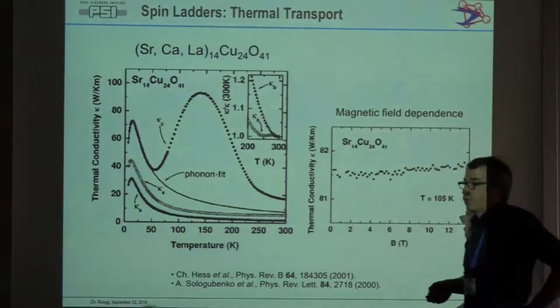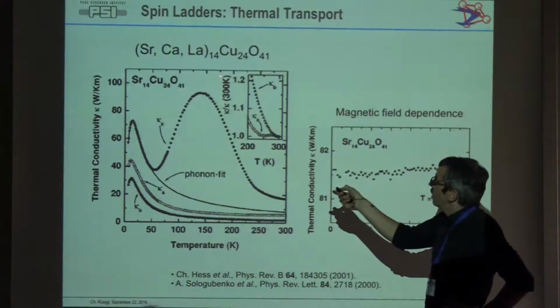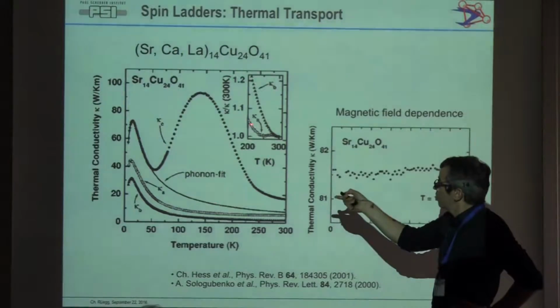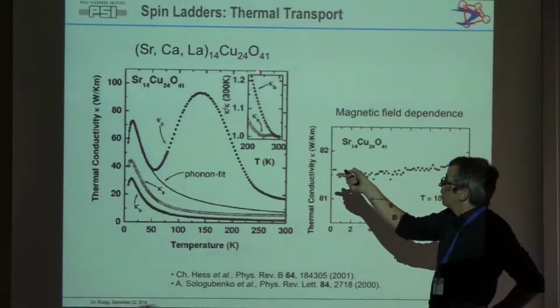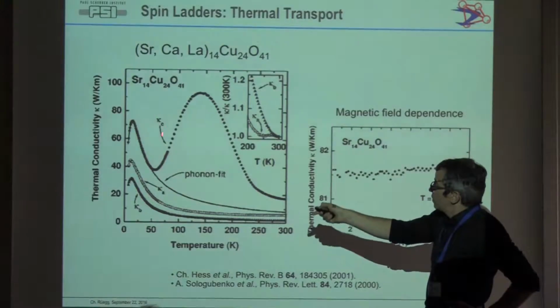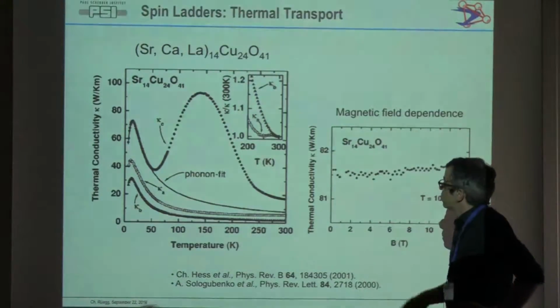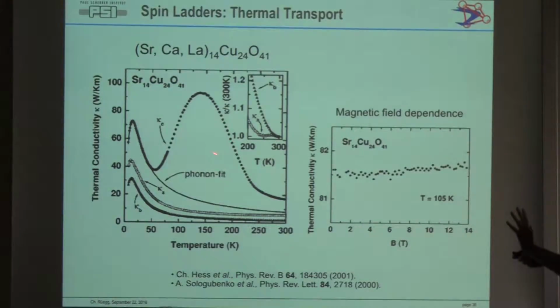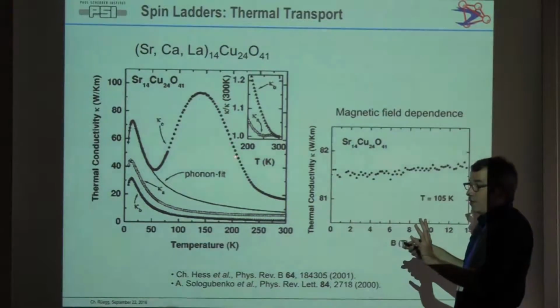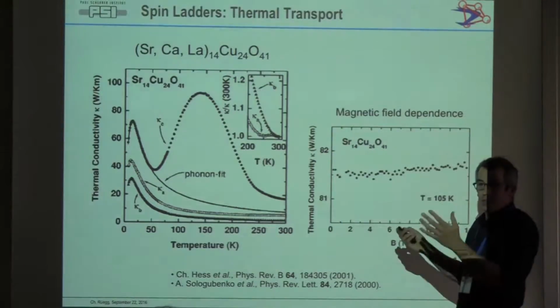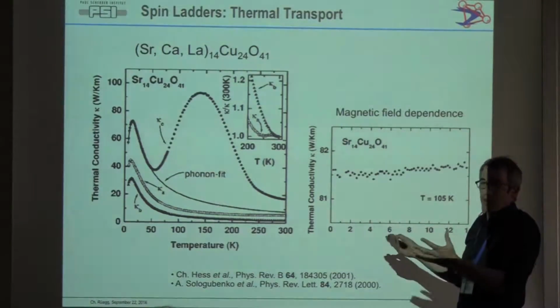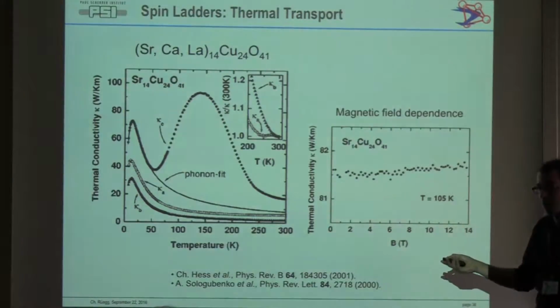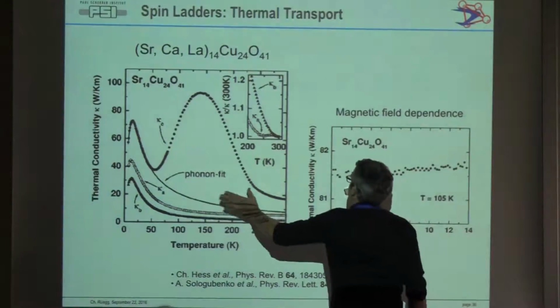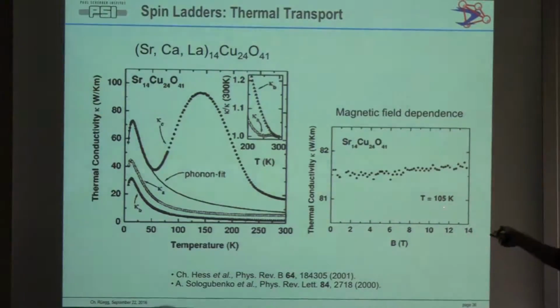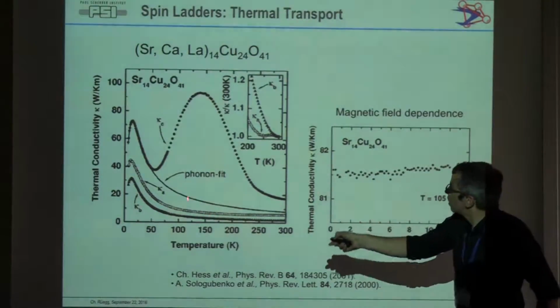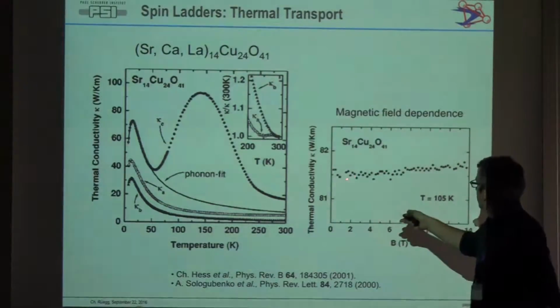That's the only thing we've tried so far, and this was seen before. This is this telephone-number compound, a beautiful presentation before with examples of chains, and this is a ladder. So you see the phonon peaks, and then this huge, basically, magnon transport. Now the special thing is, of course, this material has very large exchange parameters. So if you apply a magnetic field, essentially nothing happens. J is 100 millielectron volt. That's 1,000 Tesla. So if you apply a few Tesla, nothing happens. So here, this is one temperature, 105 Kelvin, so this is somewhere here. You apply a magnetic field, nothing happens.